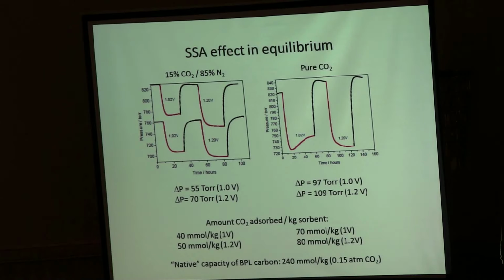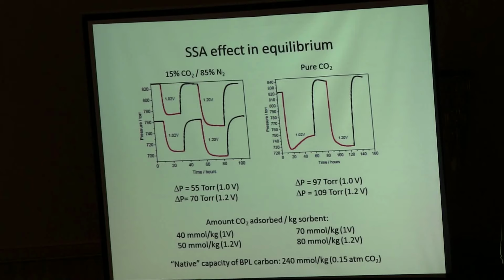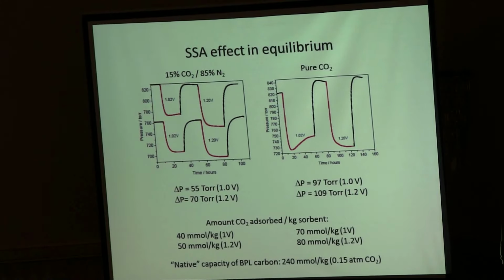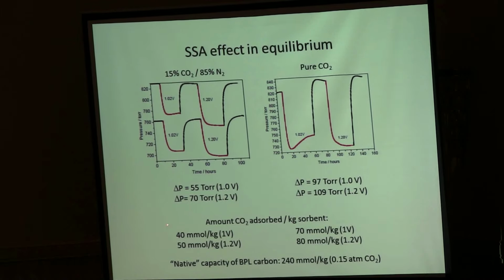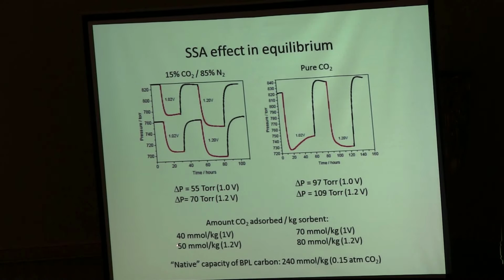Furthermore, we were interested in the question: what is the size of this supercapacitive swing adsorption effect in chemical equilibrium? To find that out, we prolonged the cycle time until we did not observe any more pressure changes. You can calculate the number of moles of CO2 that have been adsorbed from this pressure change when you know the volume of your container, and you can correlate these moles of adsorbed CO2 with the mass of the electrode material. This way you can calculate the adsorption capacity for the supercapacitive swing adsorption effect. This is, for a 15% CO2, 85% N2 mixture, 40 millimoles per kilogram at 1 volt, and 50 millimoles per kilogram at 1.2 volts.